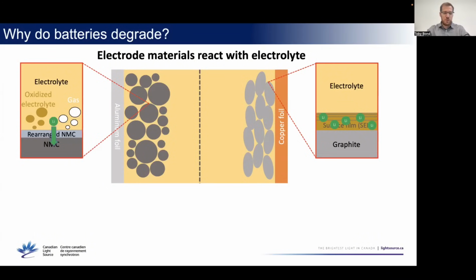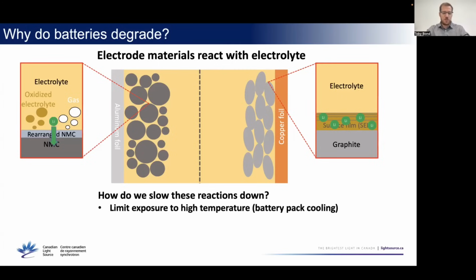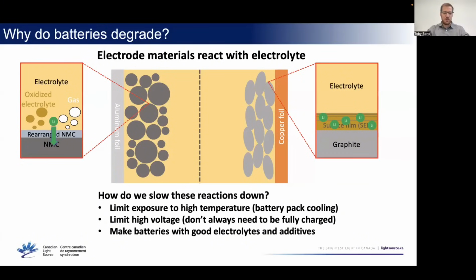So, generally we want to reduce the surface area, and we can slow down these reactions by limiting the exposure to high temperature. Higher temperatures cause faster reactions. So we do this by cooling the pack, ideally with liquid cooling. We want to limit the voltage. If your battery doesn't always need to be at 100%, it's better to leave it at a lower state of charge, generally speaking. That'll slow the reactions down. On the manufacturer side, they'll always be on the lookout for really good electrolytes and additives that they can add to make stable surface films and slow down these reactions.